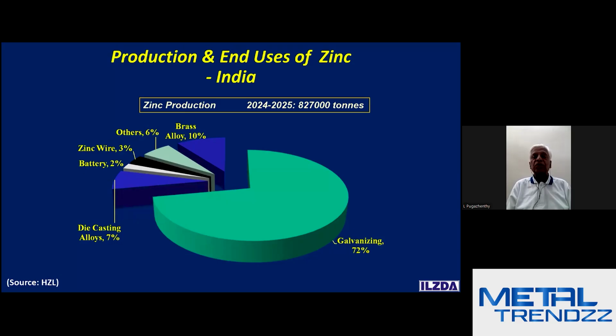And that's why zinc is used for various coatings, not only galvanizing, zinc spraying, zinc-rich paints, electroplating, zinc anodes for cathodic protection. Everywhere you're using zinc in different forms. So that's the beauty about zinc. So 72% zinc goes in galvanizing various types of products, sheets, structures, pipes, wires, miscellaneous, GI buckets, a lot of things are under this category, galvanized 72%. And brass and other alloys are around 10% in India. Die casting 7%, which I expect will see a big growth in the coming years.